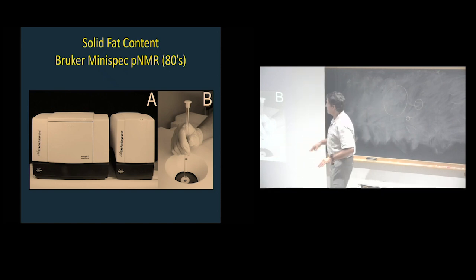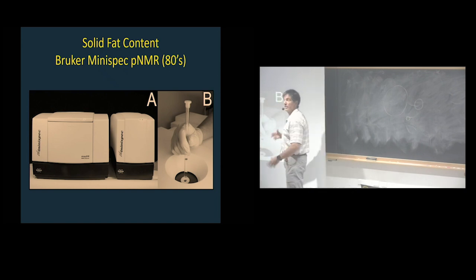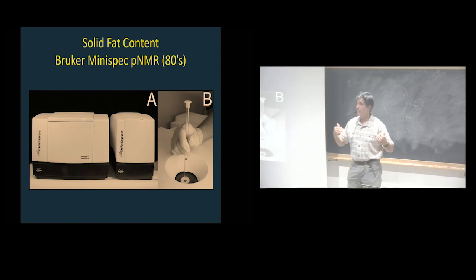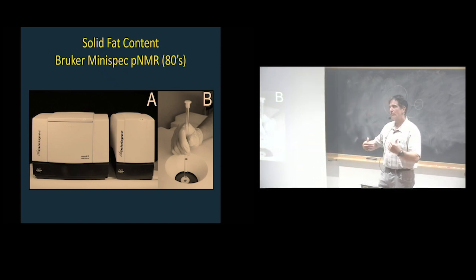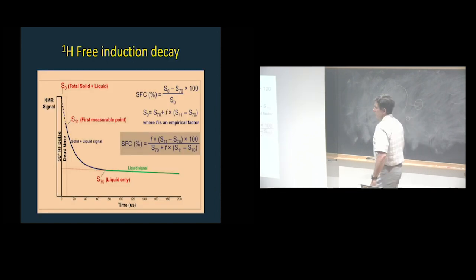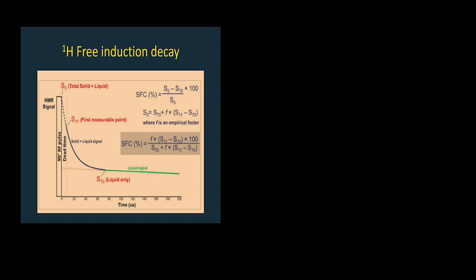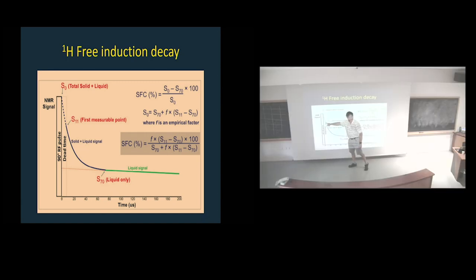It's a nightmare. So these guys developed a little, this is a 20 megahertz NMR, pulse NMR. So with a pulse NMR, you can actually determine in about 4 or 5 seconds the amount of crystalline protons, or less mobile protons, versus faster protons. You may have seen something like that. You have a free induction decay of a nucleus after an RF pulse. Then there's a dead time of the receiver, and then you see a voltage dropping, and these are the protons demagnetizing. And so in here you have both the solid and the liquid protons.